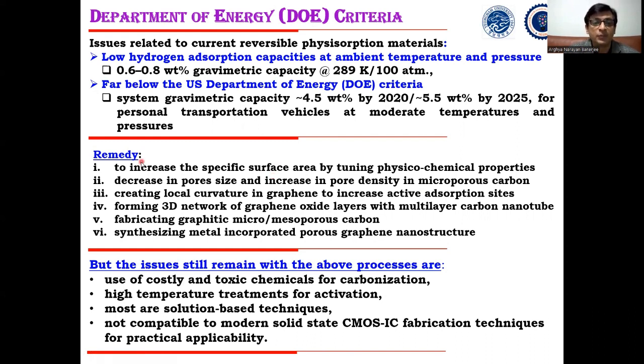So therefore, to overcome this, we need to increase the specific surface area of these carbon nanomaterials by tuning their physicochemical properties. We can decrease the pore size and increase the pore density in microporous carbon. We can increase the local curvature in graphene to increase the active adsorption sites. We can create some 3D network of graphene oxide layers with multi-layer carbon nanotubes. Also, we can fabricate some graphitic carbon, mesoporous carbon network, or we can synthesize some metal incorporated porous graphene nanostructures.